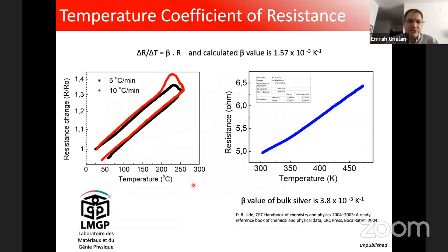And during the measurements in France, what we have also discovered is that if you heat it up and if you cool it, you can get the temperature coefficient of resistance. So the bulk silver has 3.8 × 10^-3 per Kelvin. And the nanowires, for sure, it changes with the network density, but it gives you, at least in the order of magnitude, similar temperature coefficient of resistance value.